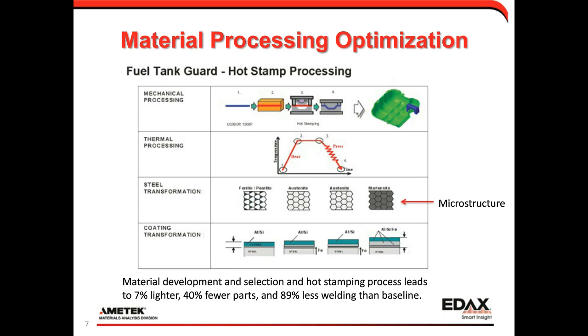And as you do that, the steel microstructure develops through that thermomechanical processing procedure. And it's that final microstructure that actually will give you your material properties. In this example, through developing this procedure, they came up with a material that was 7% lighter, 40% fewer parts, and almost 90% less welding than the baseline part that was used previously. But as they do this, you need to make sure your final result has the right microstructure. And so what we need to be able to do is measure that microstructure to help correlate that with any process development.